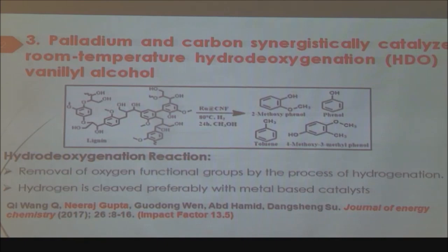Along with this, we now targeted one more compound which is derived from plant biomass, and that is lignin. This is the lignin structure, and as I told you, all these chains can be broken down, if you see these fragments. If you are able to break these fragments, you'll get different types of compounds. These compounds are all aromatic if they are not hydrogenated in the ring. So you can get hydrocarbons such as toluene. You can get phenol and phenolic products where ether or other substituents are there. So all these are phenolic products, pure phenol or toluene. And if even the ring is hydrogenated, you can get cyclohexanol also as a product. But because I don't get any cyclohexanol, or very little, I don't show it here in this reaction.